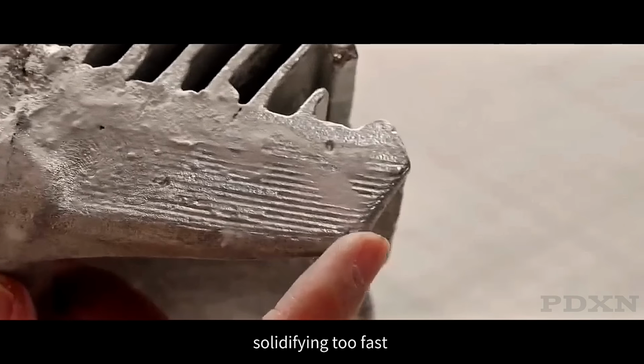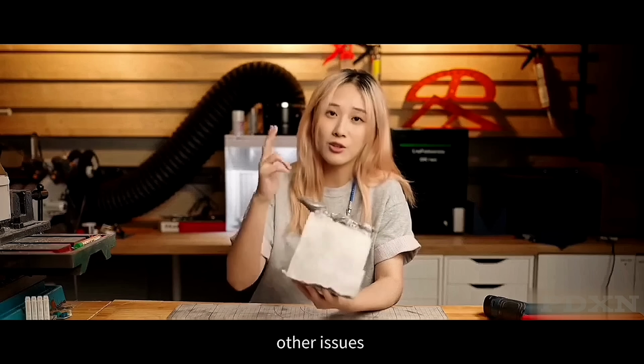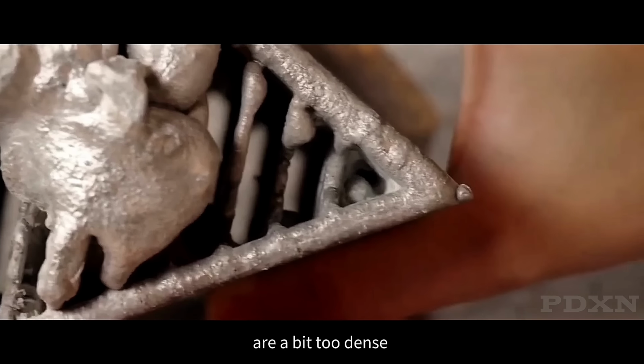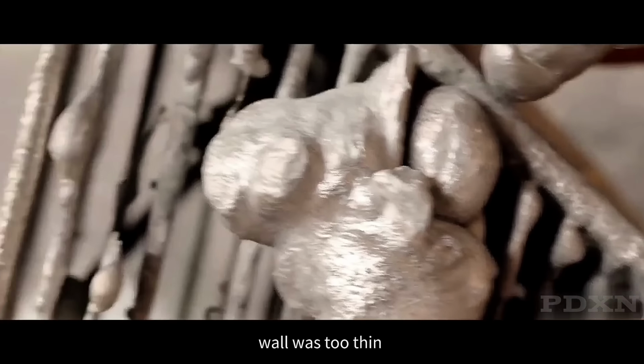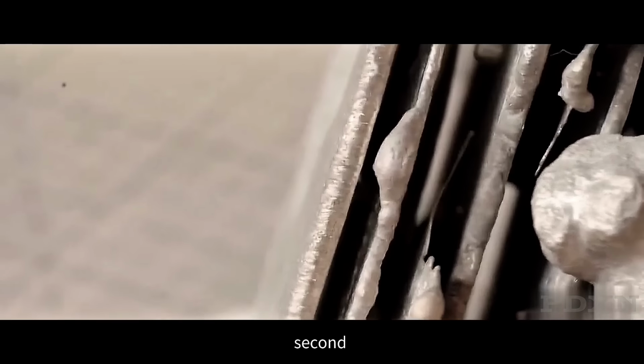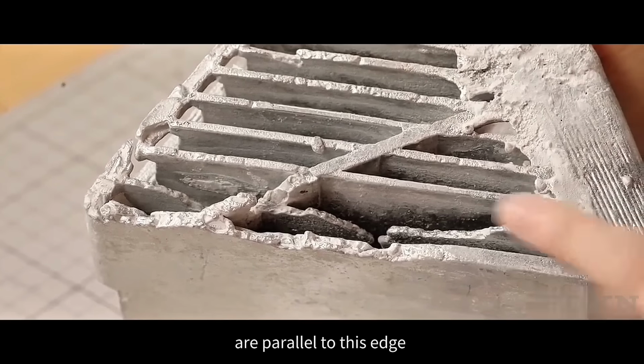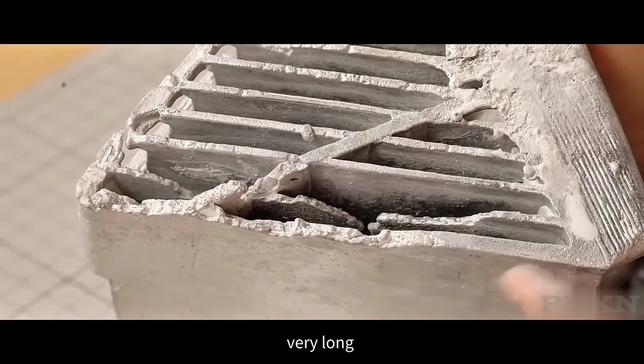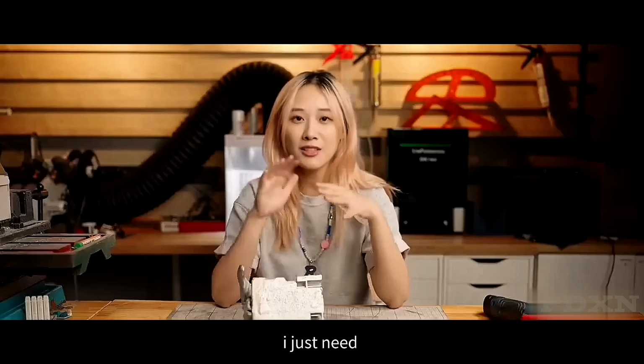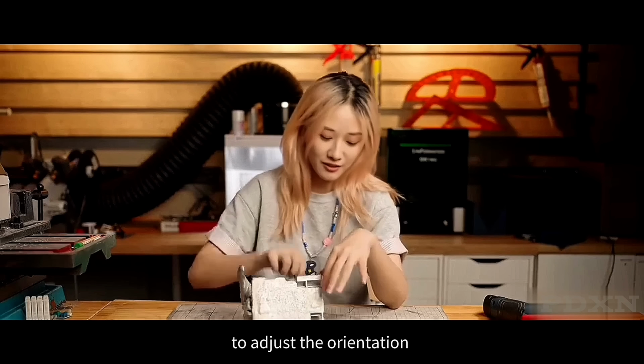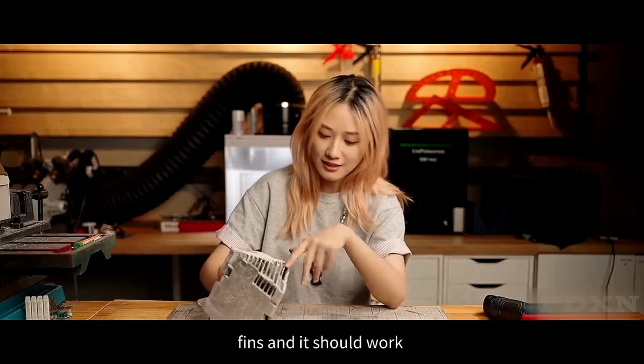Besides the aluminum solidifying too fast, there were 2 other issues. First, the heatsink fins are a bit too dense. The plaster wall was too thin, so it started to crack at the ends. Second, the heatsink fins are parallel to this edge, which makes this section very long. But those aren't major problems. I just need to adjust the orientation, thickness, and density of the fins, and it should work.